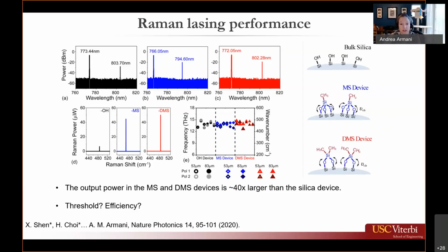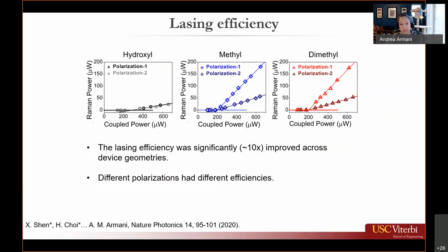Now, this change between the OH and these 2 additional surface chemistries is about 40 times larger than a silica device, but this is a single data point, right? It's just with 1 input power, and it also can't give us something like the threshold or the efficiency. So characterizing those 2 values was the next step. So we took threshold curves at both polarizations. When you have just a normal silica device, there's no difference in the 2 polarizations, which you would expect because silica doesn't have any kind of order to it.